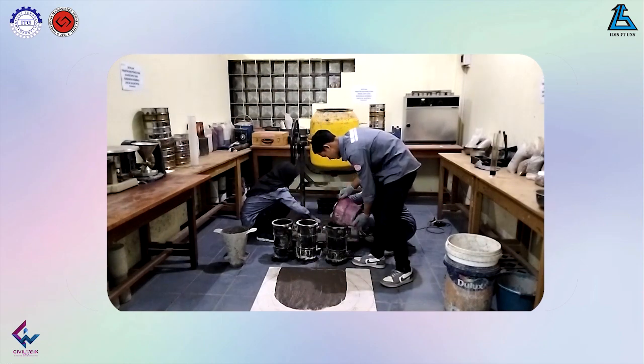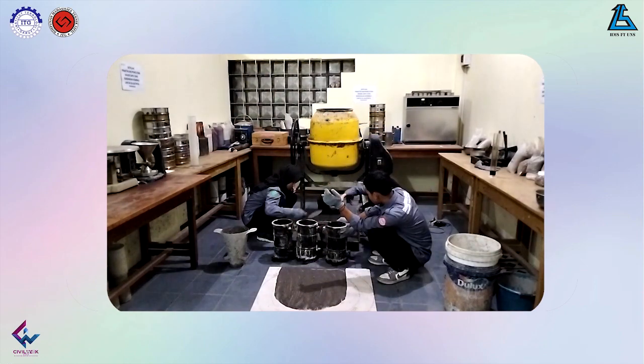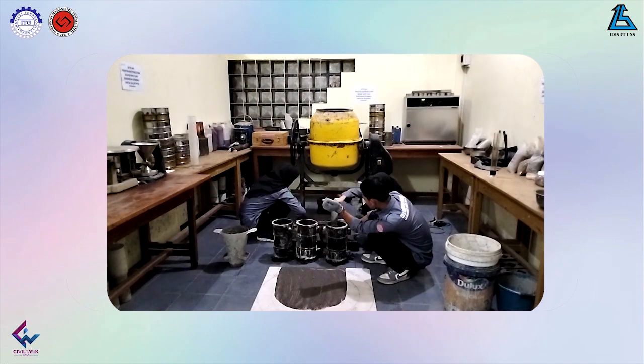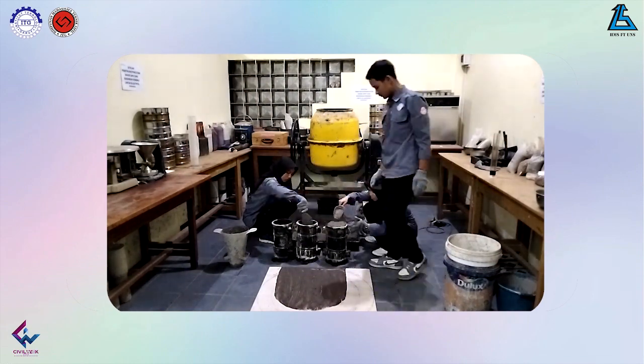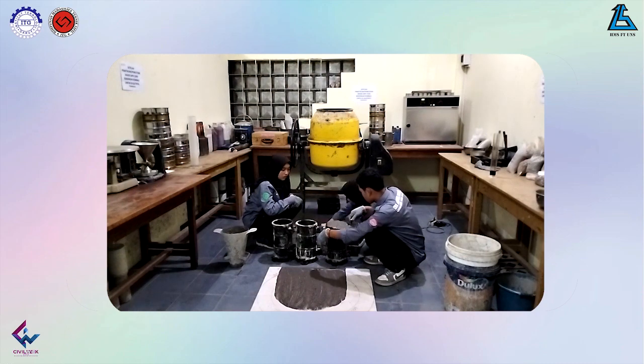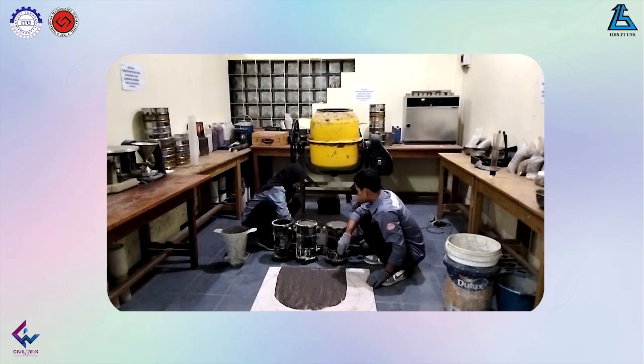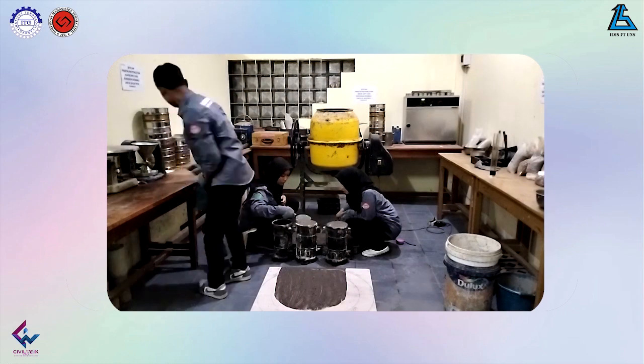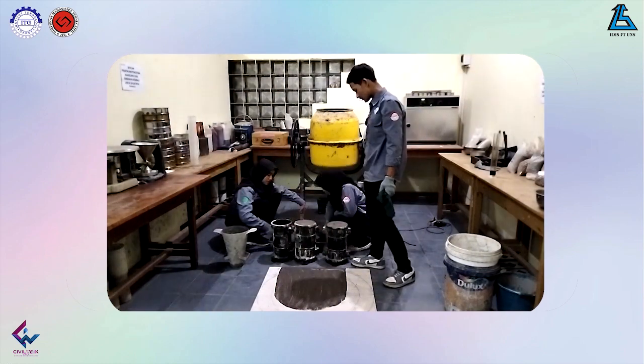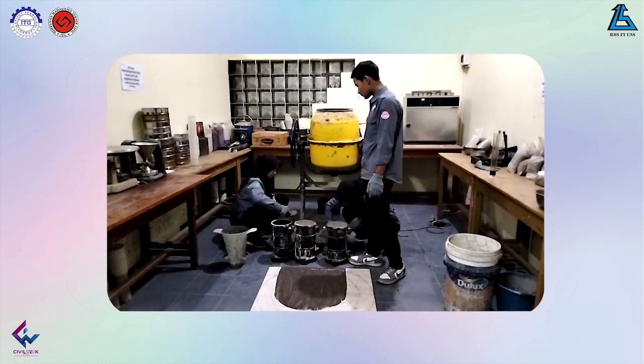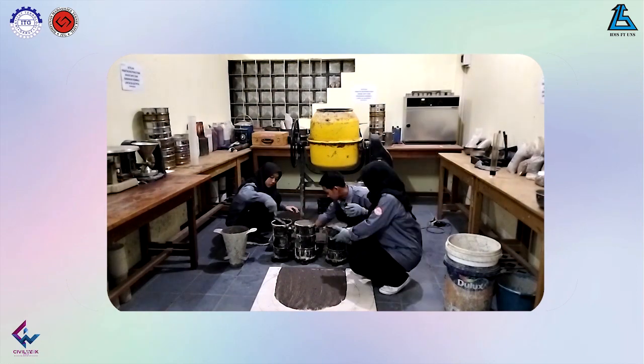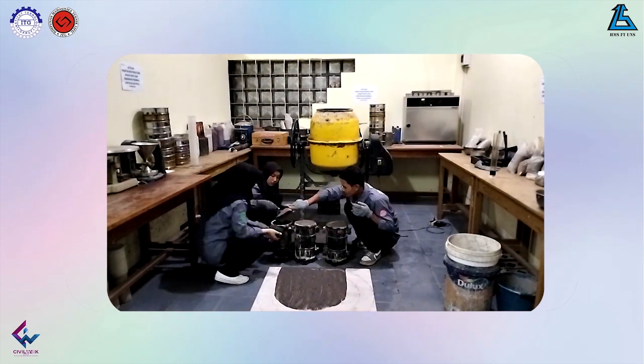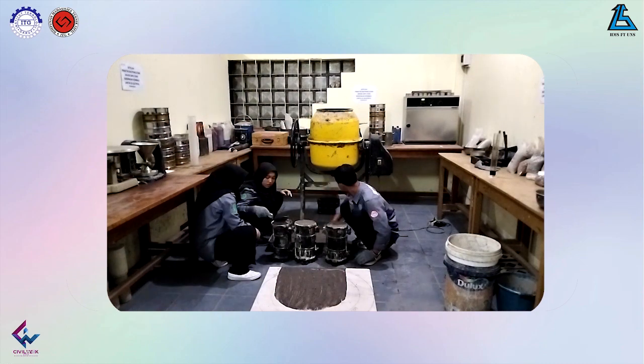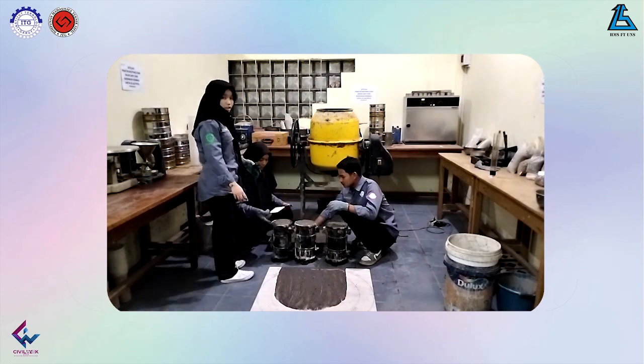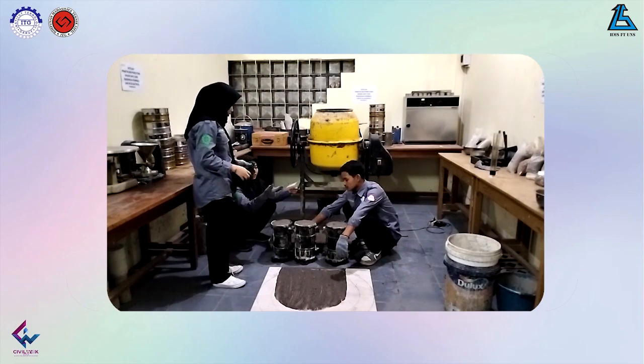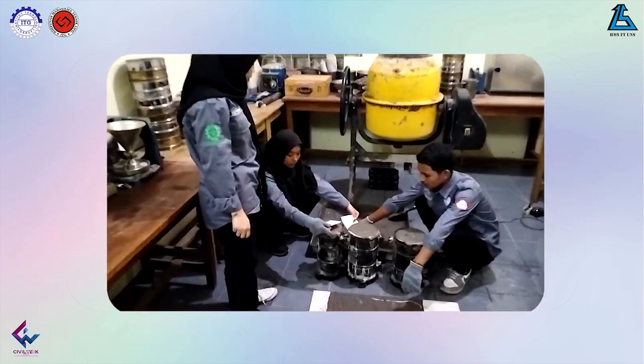Carry out a slump flow test with a slump flow target of more than or equal to 600 mm according to the standard EN 12350-8. After the slump flow test, the concrete is put into a cylindrical mold without vibration. Then put a mark on the concrete. Wait for one day to test the compressive strength of the one-day-old concrete.